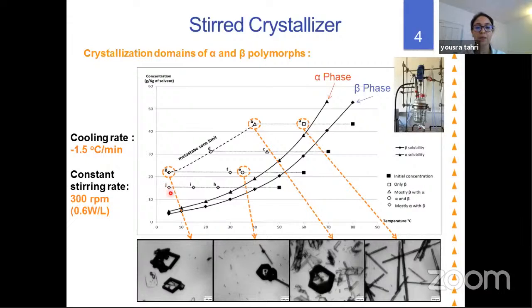So actually these experiments permit us to draw a limit of crystallization domain for both polymorphs, and we could see clearly that at low temperatures, we had the preferential crystallization of the alpha phase, which is the metastable phase, while at higher temperatures, we had the preferential crystallization of the stable phase, which is beta. And we could say at the end that our system followed the Ostwald rule of stages only at low temperatures.